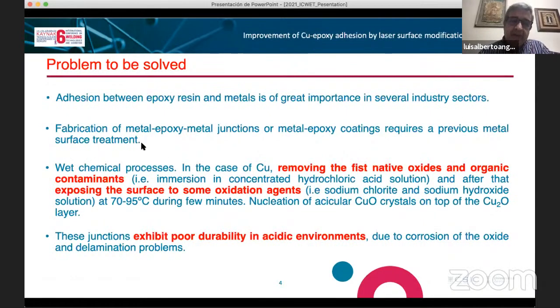So usually to fabricate good joints between copper and epoxy, we need to prepare the surface. Okay, so we need some chemical processes. In the case of copper, we have to remove the native oxides and organic contaminants, mainly by immersion in concentrated hydrochloric acid solution. And after that, we have to expose the surface to some oxidation agents.